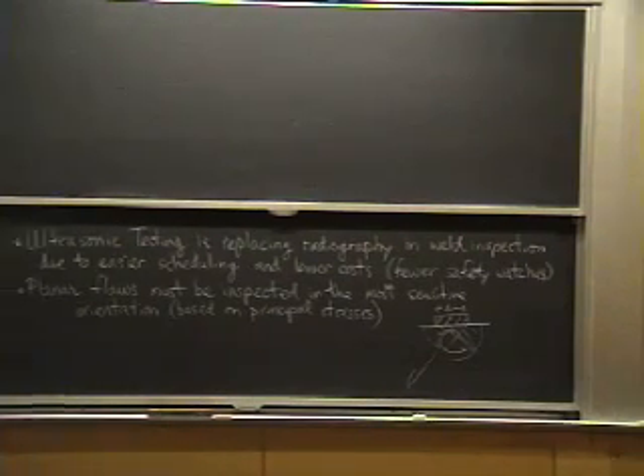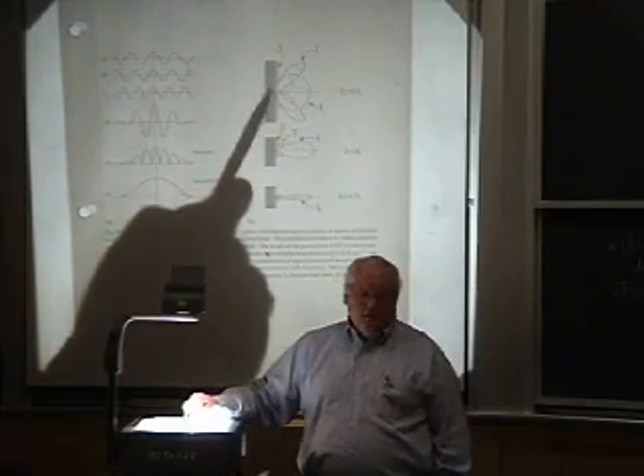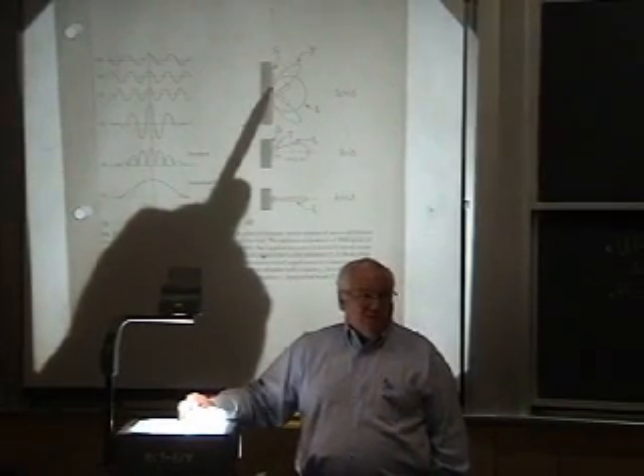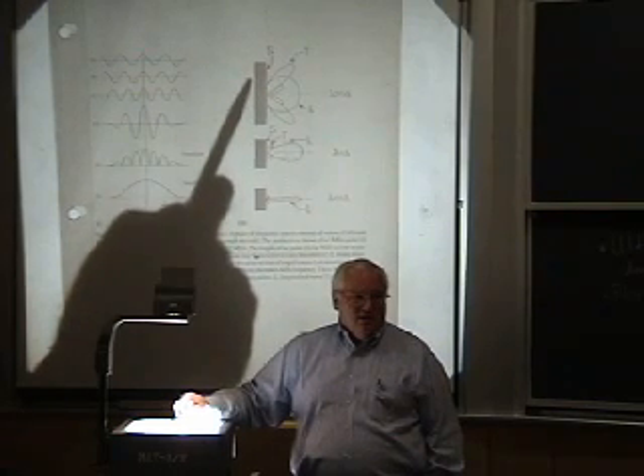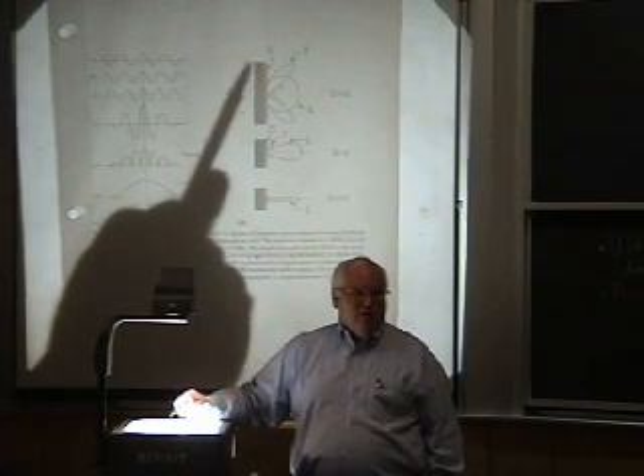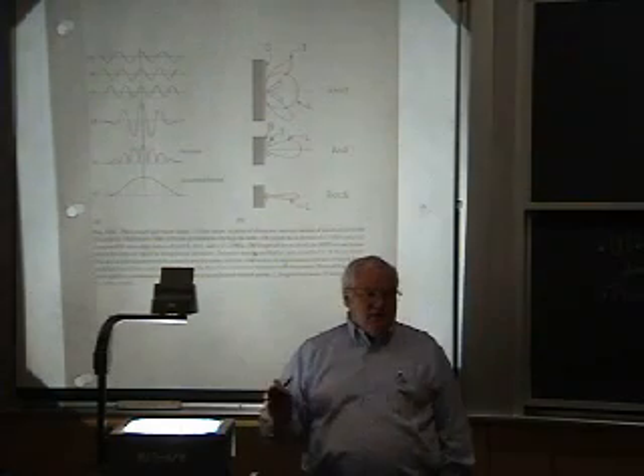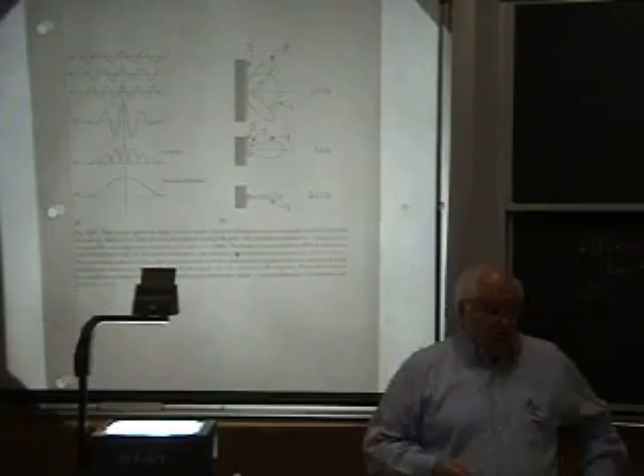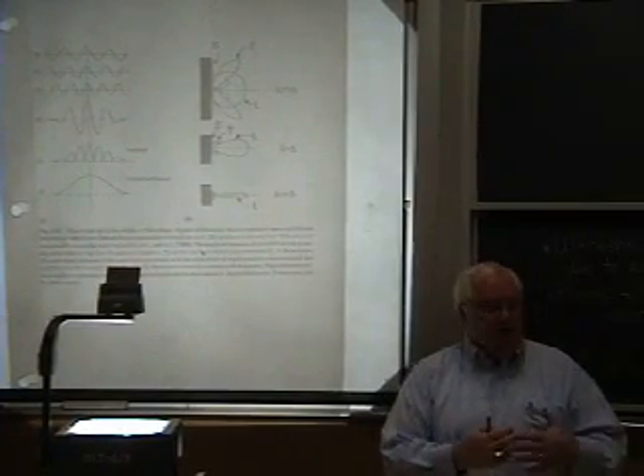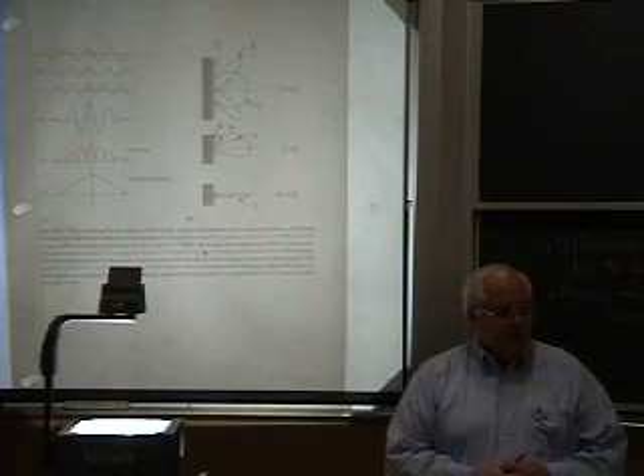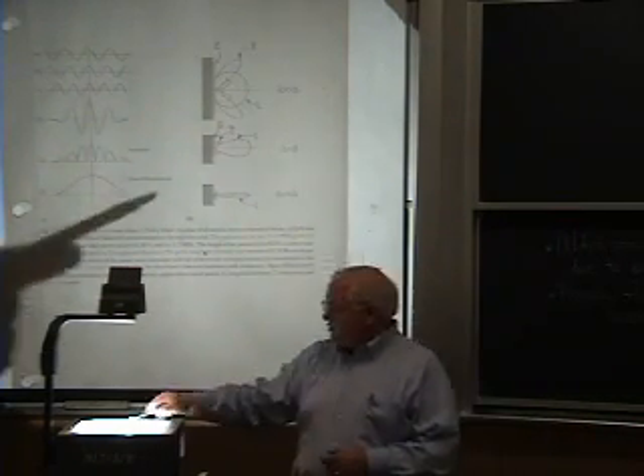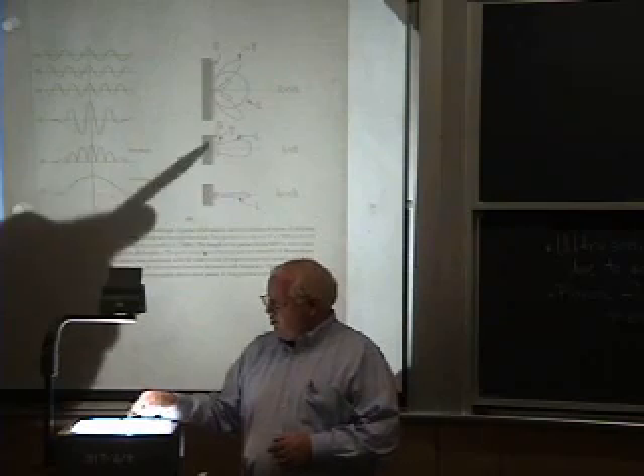If you're trying to measure in the near field region, well, what is the near field region? If you're at a couple of megahertz, the near field region might be something on the order of a millimeter or two. So it turns out ultrasonics are not very good for detecting small flaws on the surface. We have other techniques to detect small flaws on the surface. Ultrasonics are really best for measuring several millimeters below the surface. That's just because this is the near field, and this is the far field, and this is the transition in between.